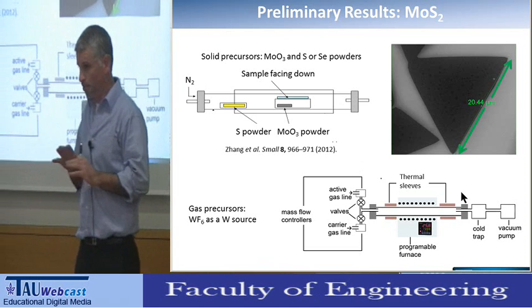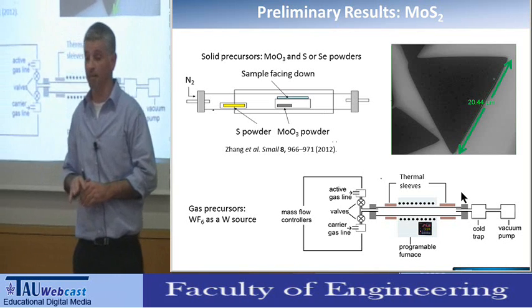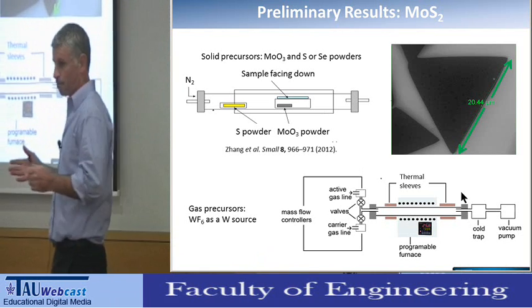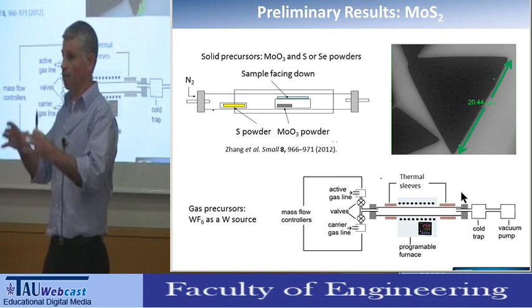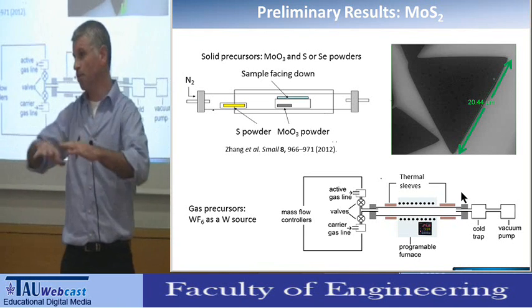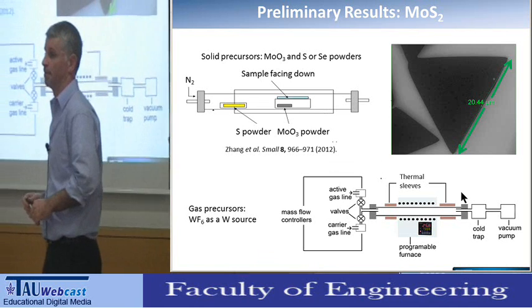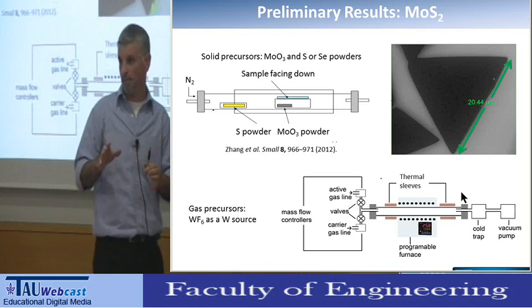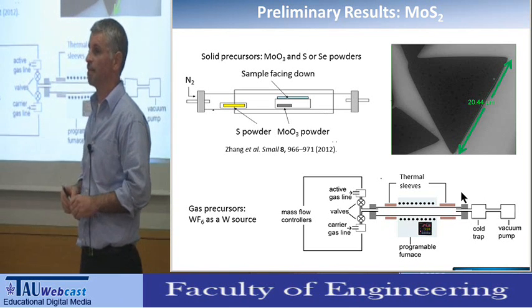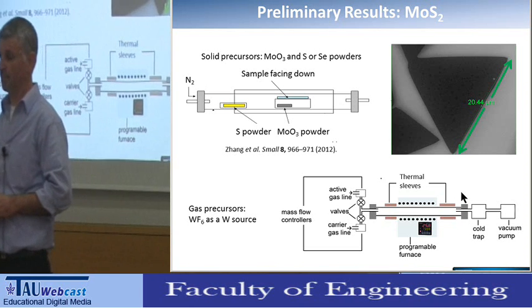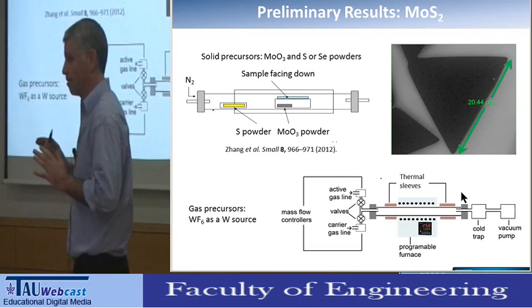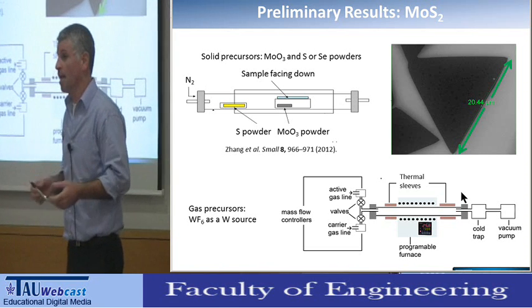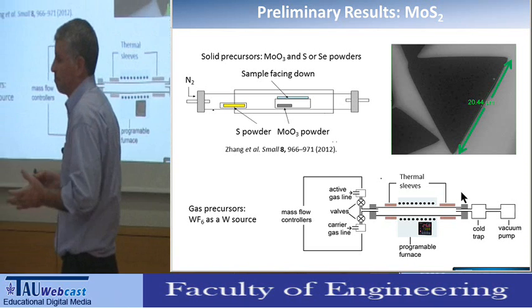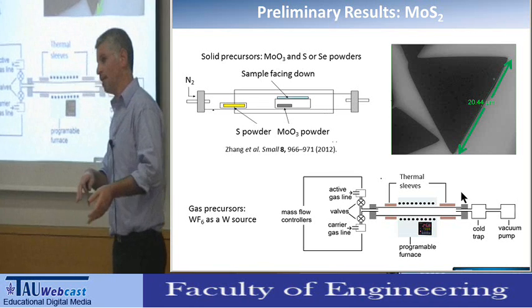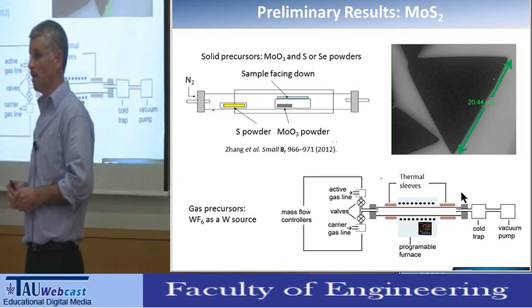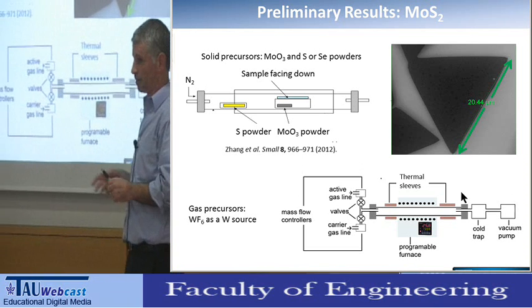Other layered compounds, there is no way to grow them at a single layer level, and when growing them at the few layers level, they usually appear first as single domains with different numbers of layers, but then they merge together to form a homogeneous film. Graphene is the only material right now that can be synthesized at the single layer level very consistently. I don't know of any work like that. I guess that they can be. I know that for graphene many people did that. I guess that you can use hexagonal boron nitride as well. I don't know about the stability of other layered compounds. That's also something that you need to check.